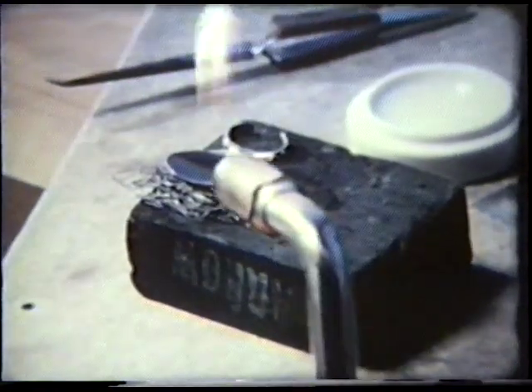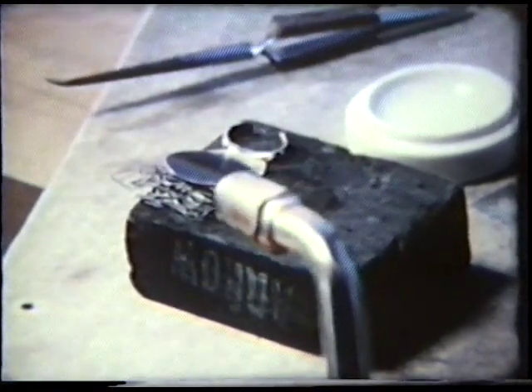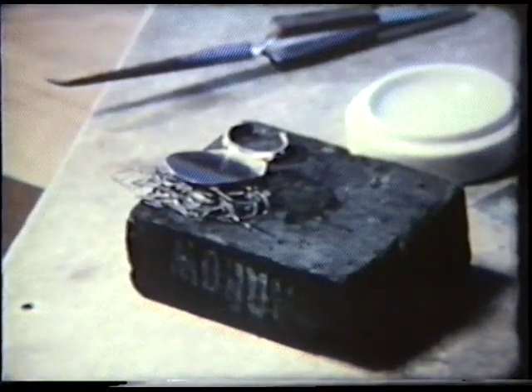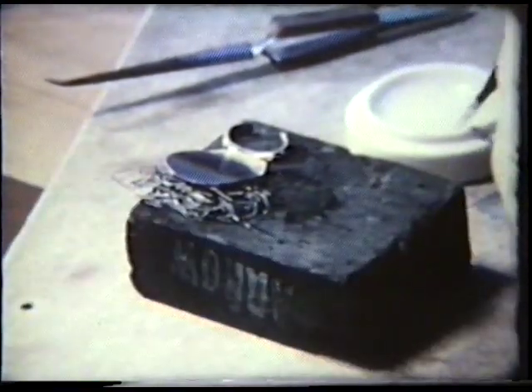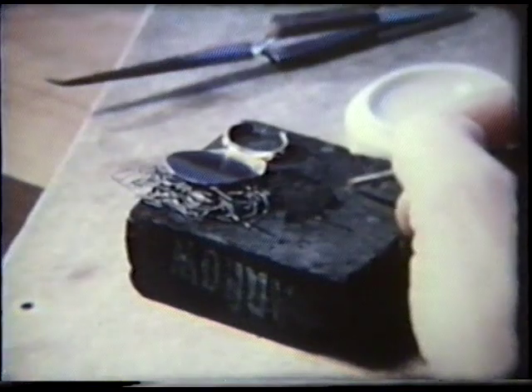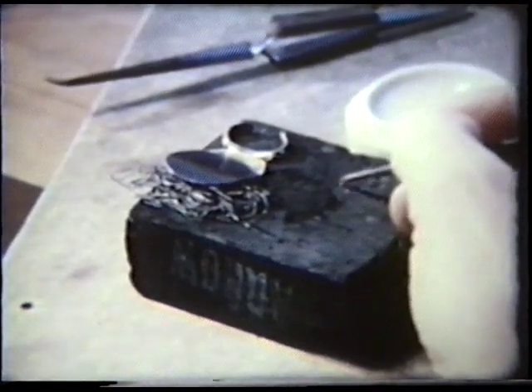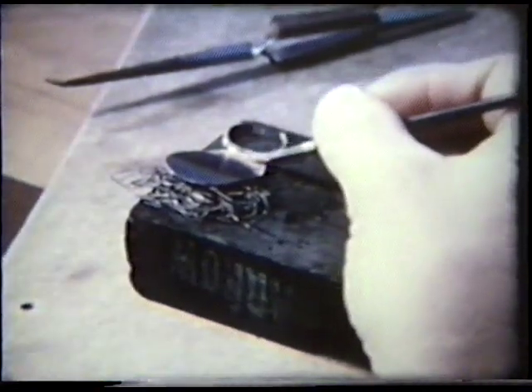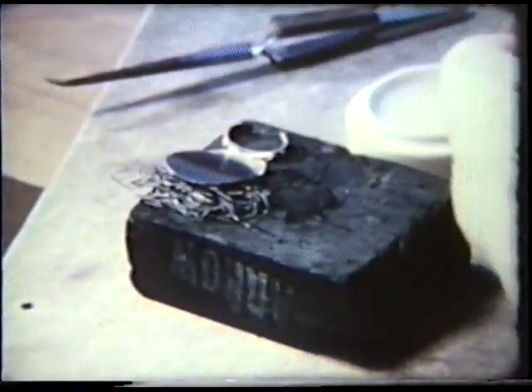The two pieces are positioned on a charcoal block supported by a nest of iron wire. The torch flame is used to remove any grease from the joint. High-temperature gold solder in the form of grains is applied with a brush at intervals along the joint, and the joint is flushed with flux.